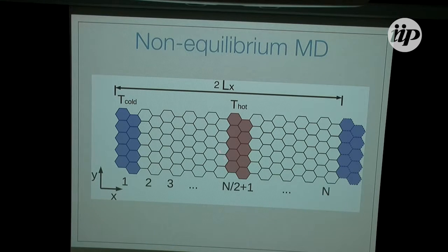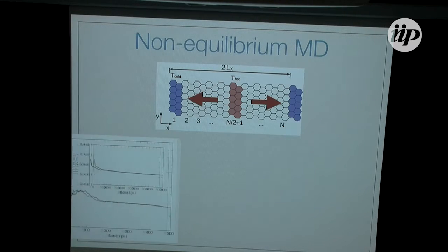So we did this with periodic boundary conditions. Instead of having a hot reservoir on one side and a cold one on the other, I put the hot reservoir at the center, and then I have two cold reservoirs at the ends of the system. This is actually just the image of this one, because I'm using periodic boundary conditions in the simulation. So the heat flows from here to here and then from here to here. My heat flux divides in two parts, but since these two parts are equivalent, the heat flux is essentially the same for each side.